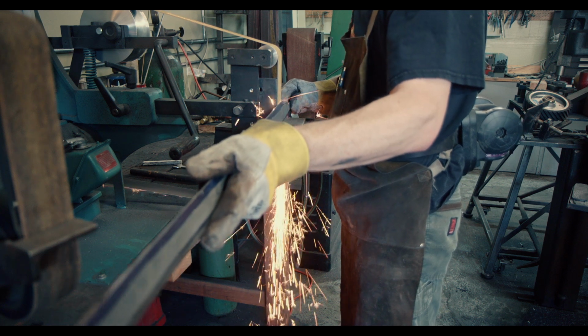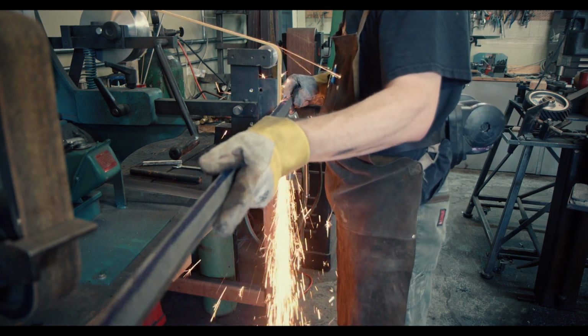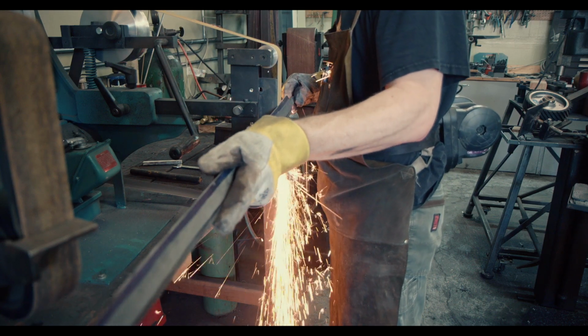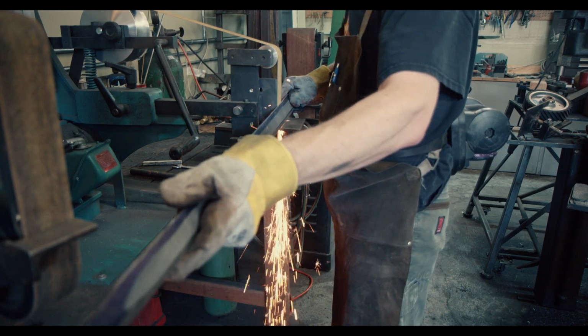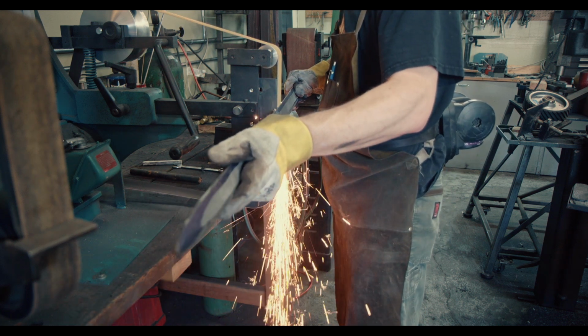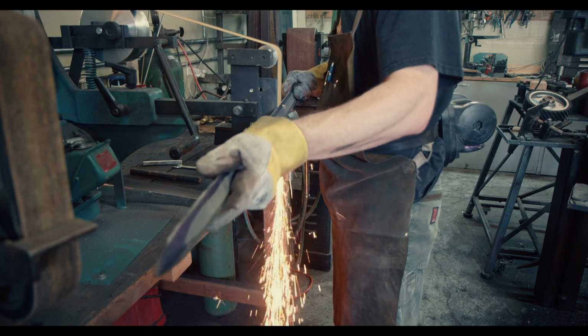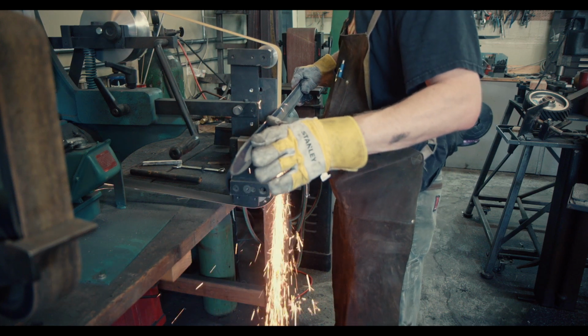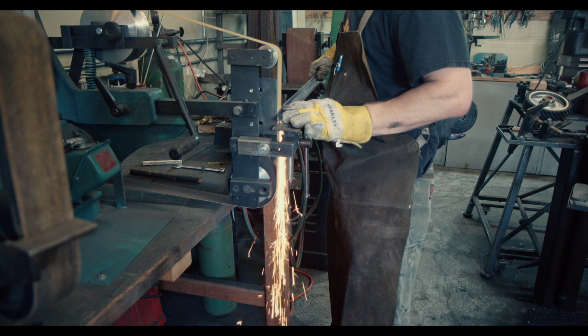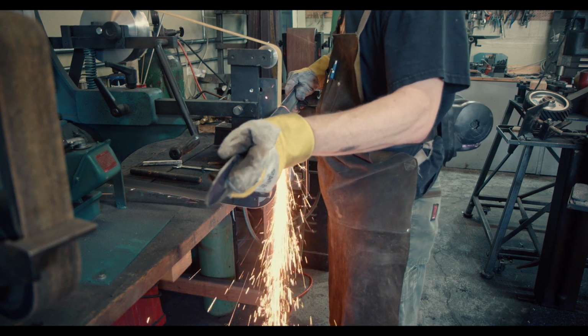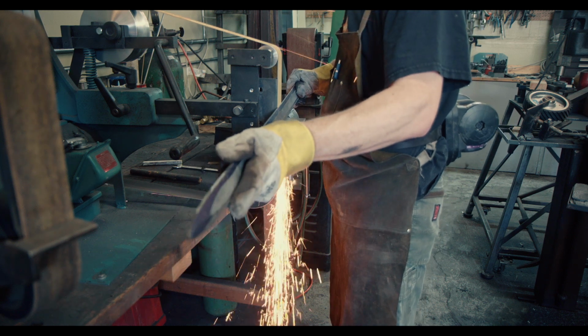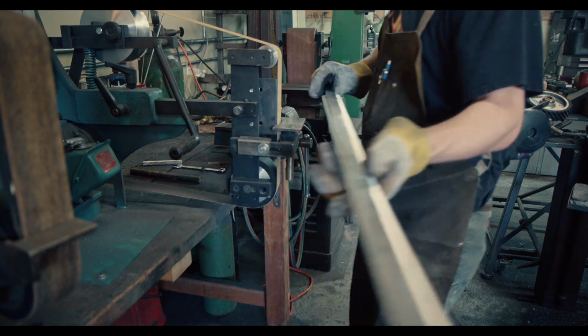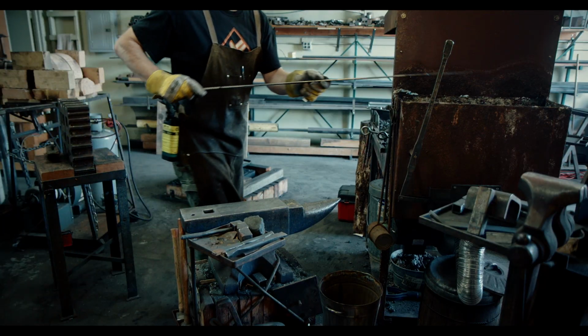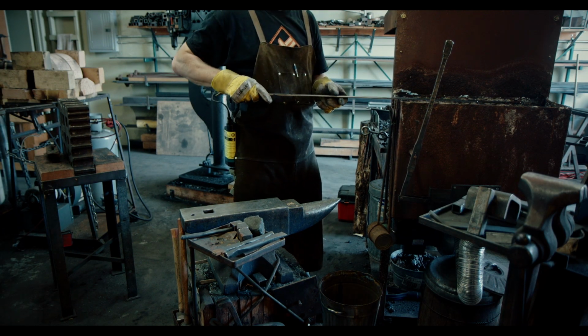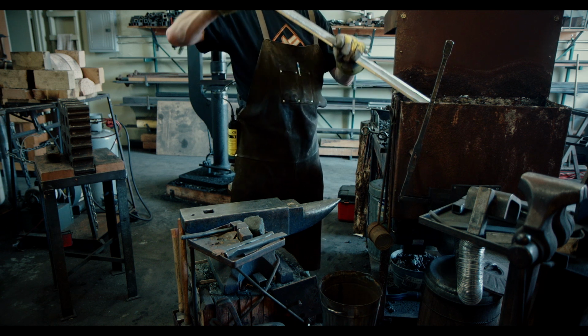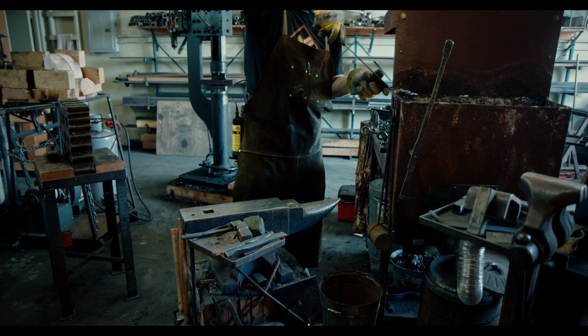I mentioned before that carbon is necessary for steel to harden. The amount of sparks created on the grinder are a good indication that this steel has a lot of carbon. With a sword of this length, it is somewhat difficult to maintain a completely straight edge, so I often need to pause and take a look. Usually I'm reasonably close to straight, but every now and then I need to compensate. You may notice that I'm wearing gloves. That is because grinding creates a lot of heat, and before the sword has been hardened, heat is not really a problem. However, even with gloves, it occasionally needs to be cooled down.